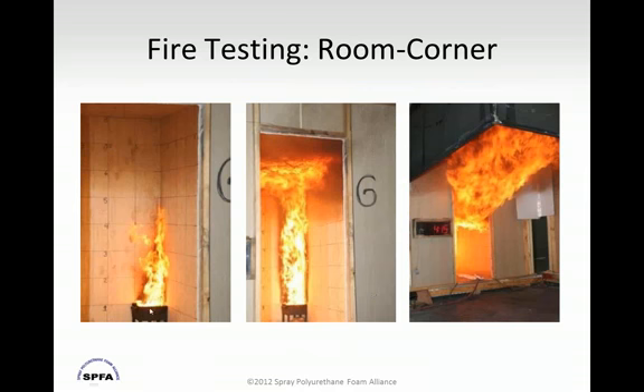In the NFPA 286 test, the fire is ignited at 40 kilowatt intensity for the first 5 minutes, and then in the remaining 10 minutes, the fire is boosted up to 160 kilowatts. If the room survives, meeting a number of different requirements, then it meets the 15-minute criteria. If it does not, then you don't have a 15-minute assembly. So this is, again, showing the progression of a fire. It'll go up the corner of the room, it'll ignite the ceiling, and eventually you'll get flashover in the room.